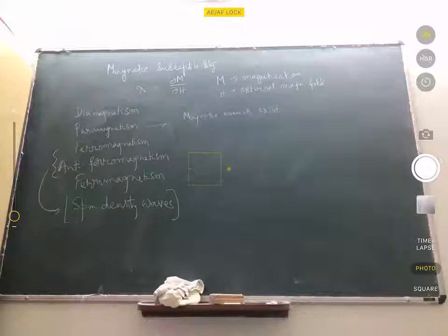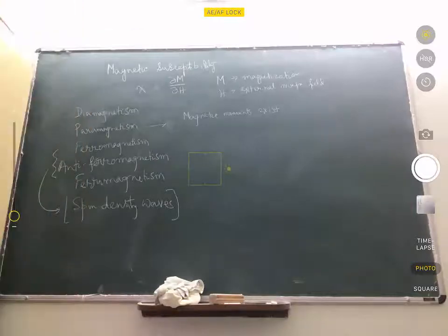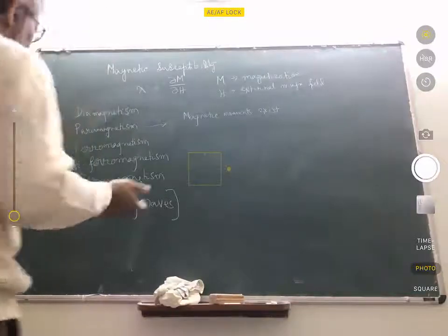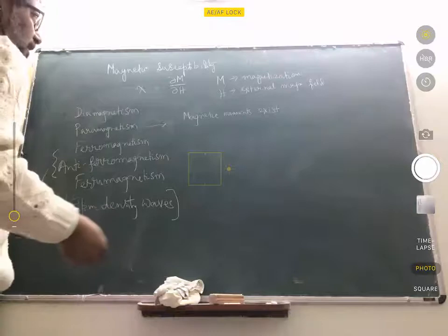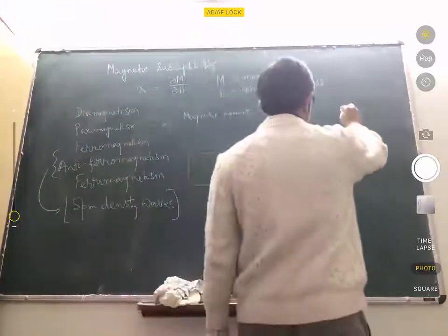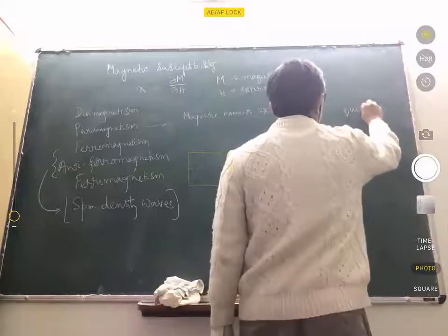So there are a lot of details on which the existence of an orbital moment depends. In particular, in systems with cubic symmetry, the orbital moment is almost non-existent. For example, take a 3D transition metal atom. In an isolated atom, of course, you will in general have an orbital moment, except if the filling of the d orbitals is such that it happens to be zero. But when you put that in a crystal which has cubic symmetry, most often you find that the orbital moment is zero. And that phenomenon is called quenching.